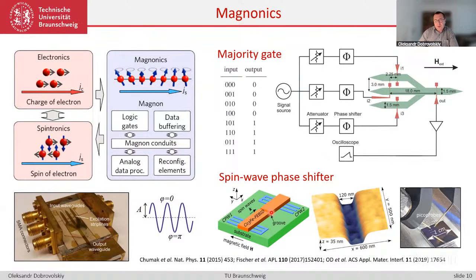And in the middle of the conduit, if it is exposed to the action of a focused gallium ion beam, one can mill a part of the film to reduce its thickness. In addition to that, it suppresses magnetization locally because of incorporation and stopping of gallium ions. So these two parameters, conduit thickness and conduit magnetization, affect the spin wave dispersion, but also the group velocity, which is the derivative of the dispersion relation. And this means that there is phase accumulation, so phase variation, which additionally can be tuned by the applied in-plane biasing magnetic field. So this device is then reconfigurable depending on the strength of the in-plane magnetic field.